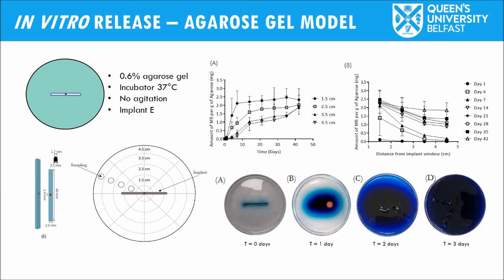But if we quantify at different times, at different distances, we can see that the system continues releasing for 42 days. Okay, for 42 days, you can see that obviously the methylene blue diffused through the tissue, but it continues being released for 42 days. So that is a more respectable time frame. Obviously, this type of implant cannot be used for therapies that require long-term release, but they can